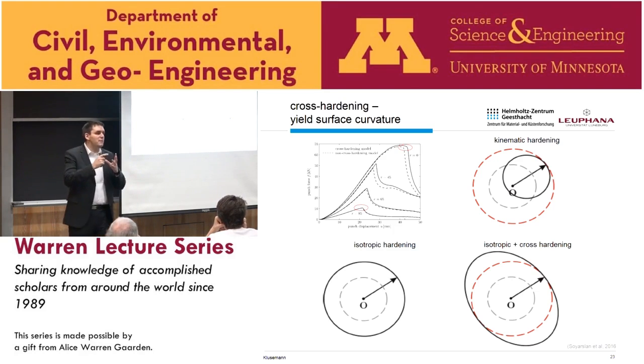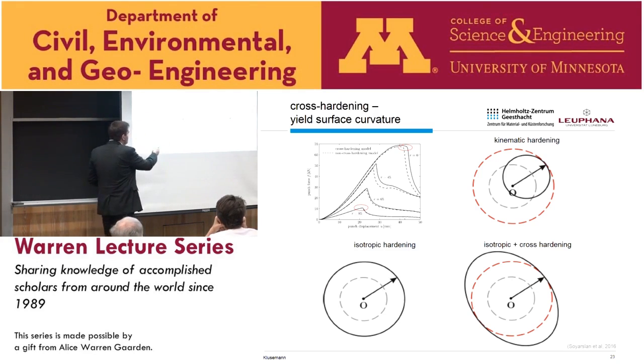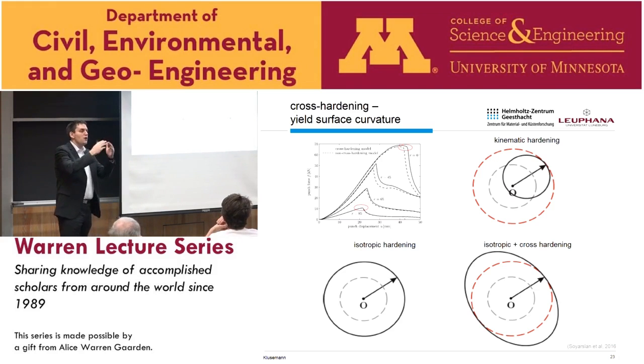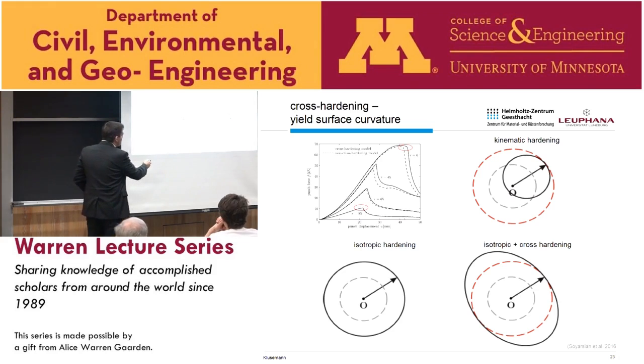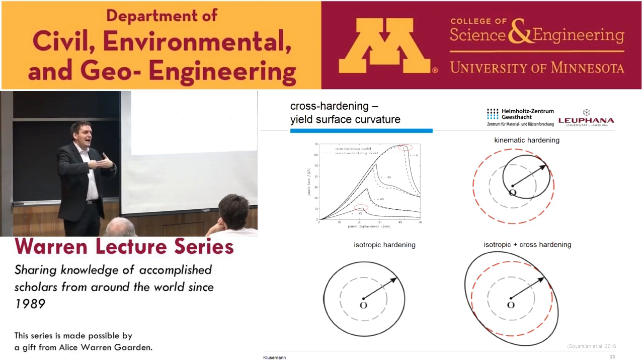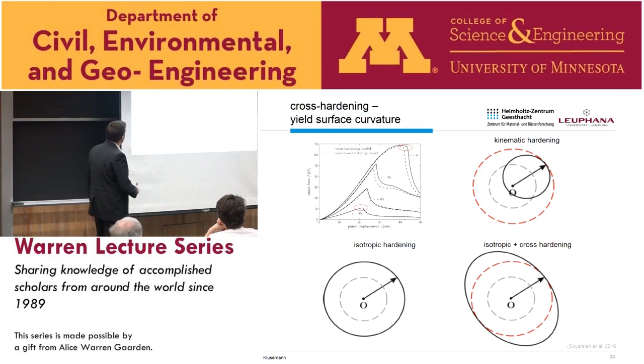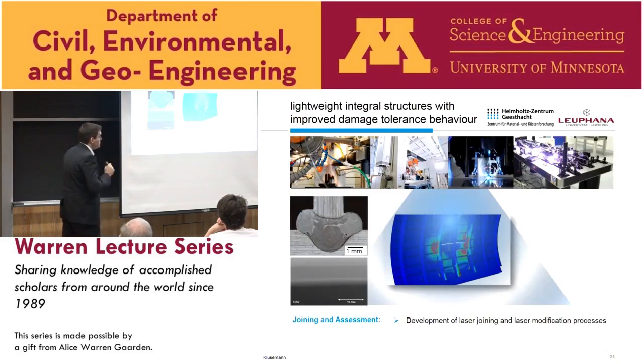And what is actually the reason why we have no difference here and a strong difference there? Well, we attribute this mainly to the yield surface changes. When you imagine a classical isotropic hardening, you have simply an increase of your yield surface. When you have a kinematic hardening, you just have a shift of your yield surface, which means your curvature is not changing at all. And when you have this isotropic plus cross hardening, you get a kind of flattening of your yield surface, and from a mechanics standpoint at least, when you have a flatter yield surface, this means you have an increased formability condition. So the extreme would be the vertex. This would be the extreme.